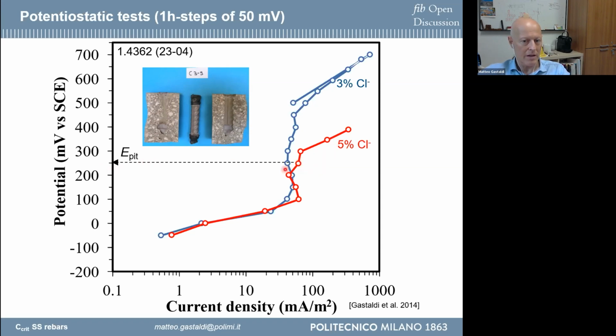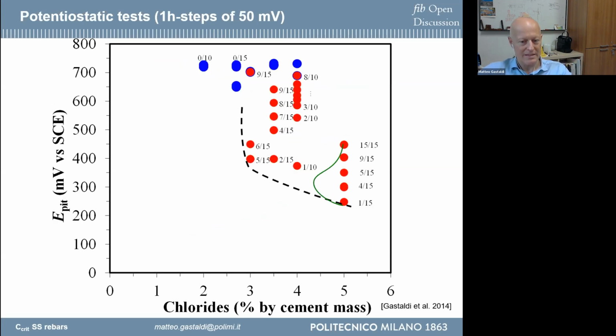And so this is when you have the change in the slope of the diagram. You can detect that here you have the initiation of corrosion, the pitting corrosion initiation. This is the parameter that is normally considered in electrochemistry. So if you repeat this test for a lot of chloride contents, changing the potential and so on, you can obtain the data to draw the diagram in this condition. So, in a test with a change of potential of 50 millivolts with a step of 1 hour.